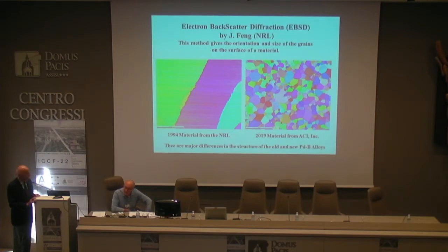The difference in texture may be due to the fact that you rolled your ingot before annealing it again. When you do rolling and annealing, you get such a new structure. If we cook the material at 650 C for 2 hours, Imam determined many years ago that you will anneal out dislocations and soften the material. If you go to 800 C for 2 hours, then you get grain growth.